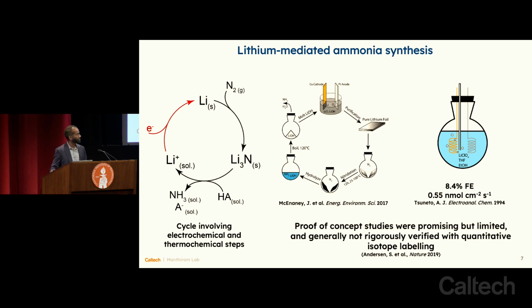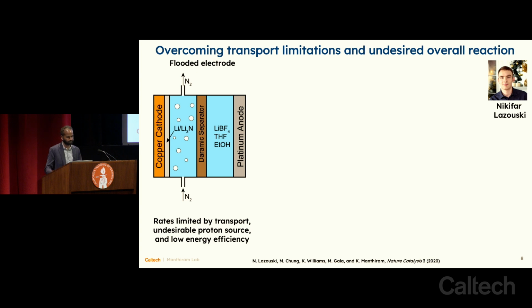We were really intrigued by this isolated report that demonstrated that a one-pot reaction could perhaps be done. The issue here was that the Faradaic efficiency was really low. It was just 8%. So just 8% of the electrons were going to the right place. The rest were going towards undesired reactions in this process. And the rate was just 0.55 nanomoles per centimeter squared of electrode area per second, which we can probably all agree is really small. So this was a pretty humble starting point in terms of electron-based selectivities and rates from where we wanted to try to make improvements.